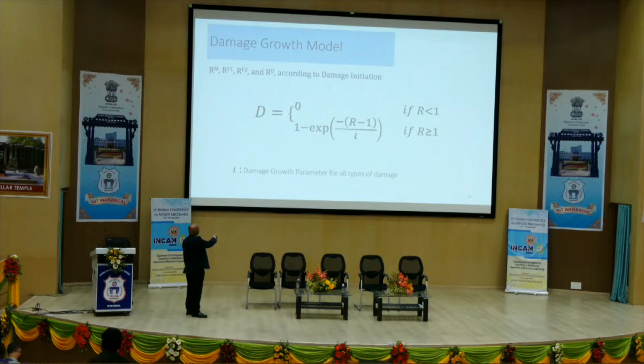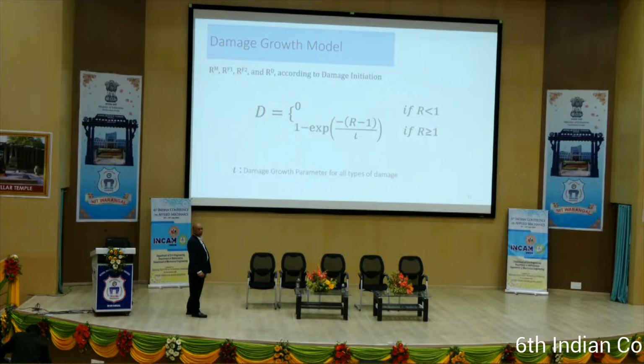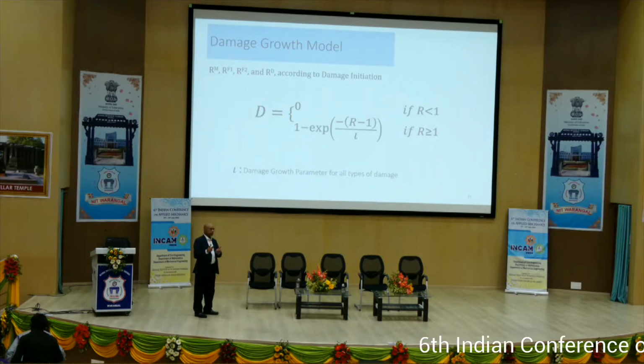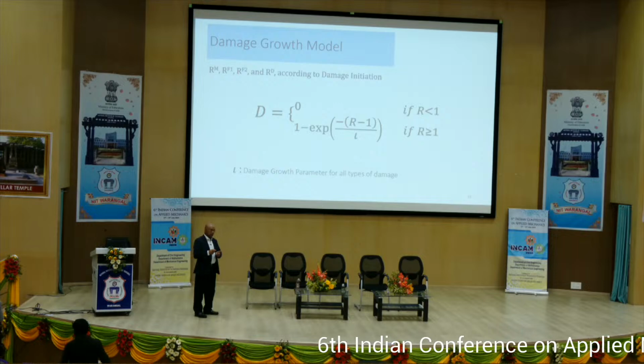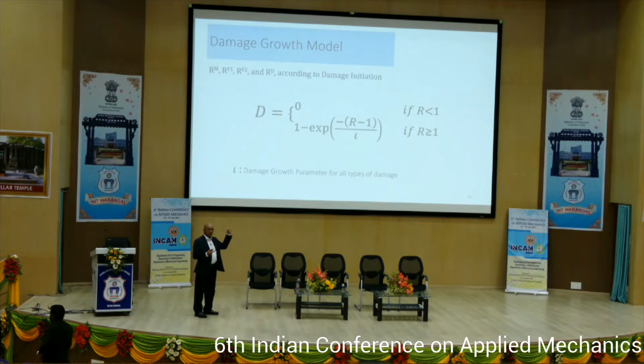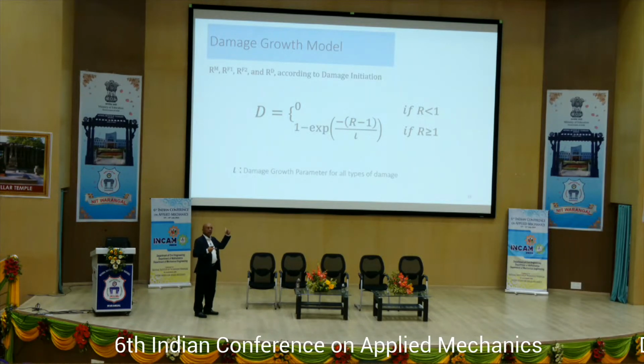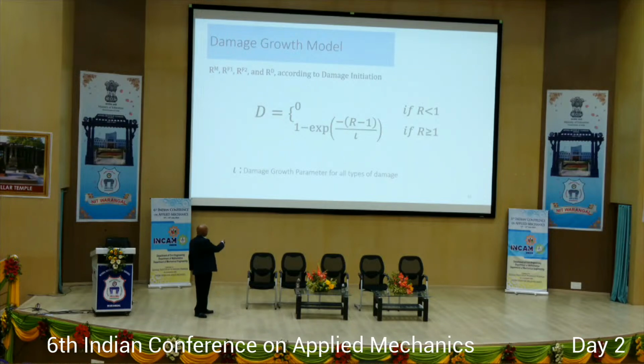You can see when R equal to 1, 1 minus 1, 0, exponent to the power 0, 1 minus 1, 0. So R equal to 1, you are initiating damage. When R is greater than 1, the damage is growing. And this equation captures that. When R keeps on increasing, the parameter iota controls the rate at which the growth occurs. The simple empirical model can do the job.